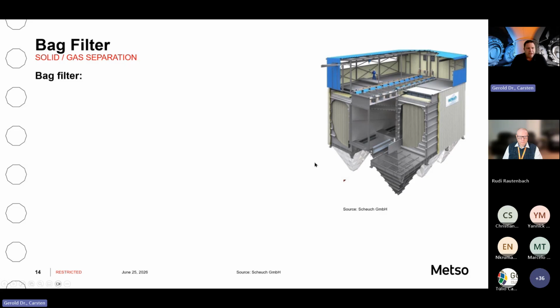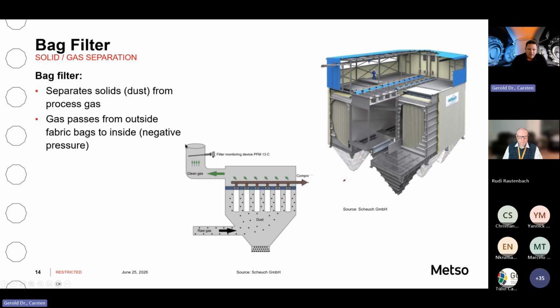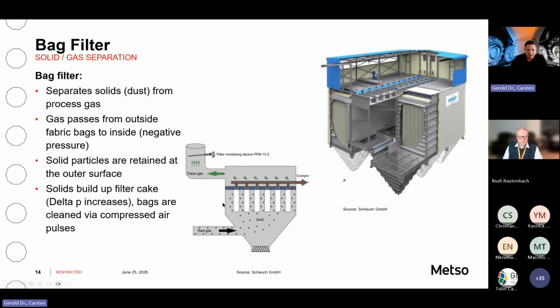Another equipment that is pretty new to you probably is the way we de-dust the systems. In this case, the example of a Scheuch baghouse, because somehow we have to get the solids out of the gas flow, and that is done in these baghouses. Simplified scheme in the bottom here. So raw gas, which is gas that is loaded with solids, is sucked through the baghouse. On the right-hand side, you see here this empty chamber in gray. And from there in the bottom, you go to the left and right baghouse compartments where you see in white the filter cloth. So the material is basically following the gas flow and therefore is finally sucked onto the bags where it builds a filter cake.